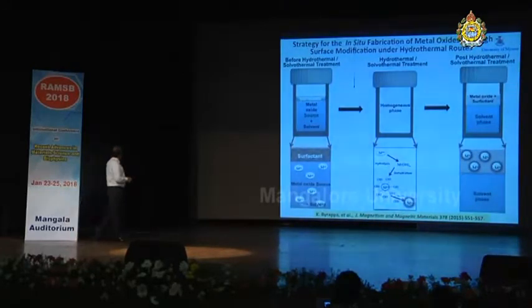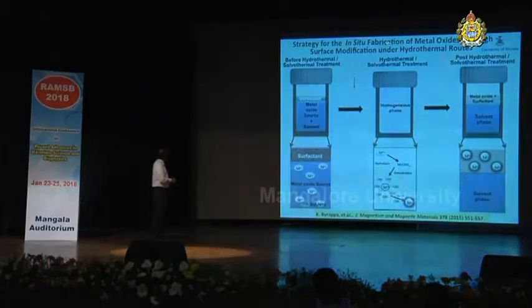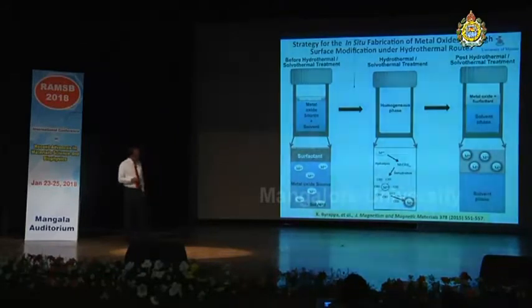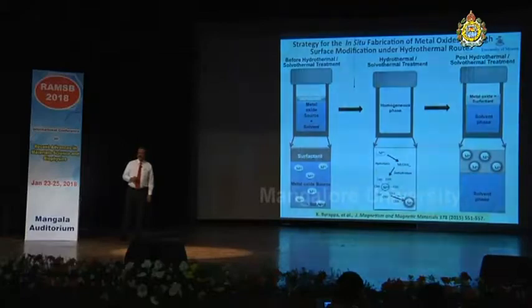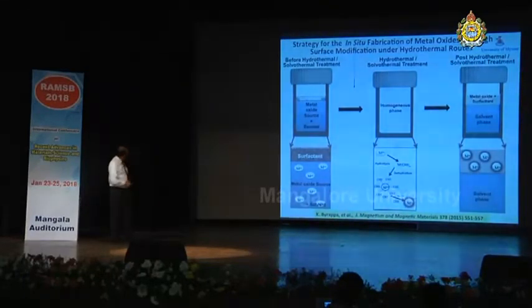Well, this is the strategy we adopt to fabricate metal oxides in situ, and also to modify the surface properties of these metal oxides. The principle adopted here is from a kitchen experience: adding a few drops of oil when boiling noodles will not make the noodles very sticky. In the same way we use some fatty organic acids, which are popularly called surfactants, and these surfactants do not allow the nanoparticles to agglomerate, and also do not allow the nanoparticles to grow in particular directions, or also it will hinder the growth of bulk or bigger particles of the metal oxides.